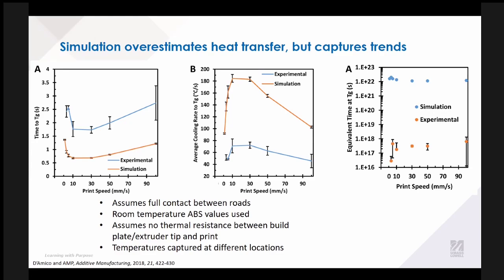We ran our simulations for a range of print speeds, that is, how fast the nozzle is printing the material, and we observe that we're capable of capturing non-monotonic trends in the time to TG, or the average cooling rate to TG. We also see the same insensitivity of equivalent time to print speed that is shown in the experimental results. I want to unpack this a little bit because there is an interesting balance here. At really slow print speeds, we have more time above TG because our nozzle is moving very slowly. We've got a lot of contact between the nozzle and our print structure, so we end up getting extra heat transfer from the slowness.